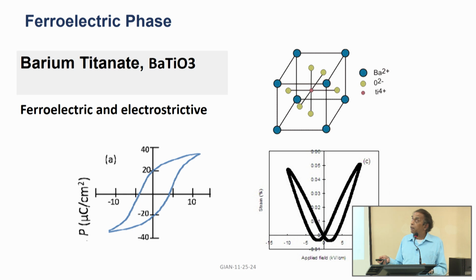And for the ferroelectric, there are several choices. Barium titanate, as I mentioned earlier, is electrostrictive. This is the strain as a function of applied electric field. Whether it's positive field or negative field, the strain is still the same, it doesn't change sign. And this is typical polarization versus electric field.